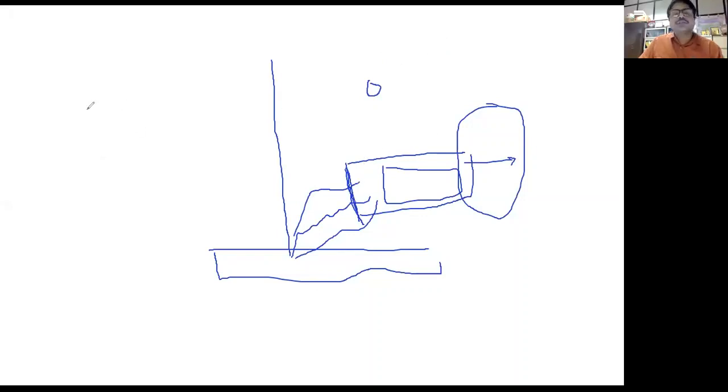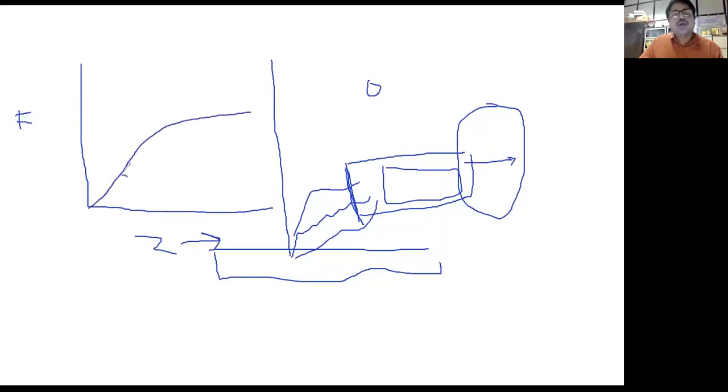And another point is the scattering cross-section for X-rays, this is called fluorescent yield. Suppose this is our curve, where this is atomic number, and this is fluorescent yield, which is basically a ratio of X-ray emission and Auger emission. I think all of you know that Auger and X-ray emission are competing processes. So when we increase the Z number, it starts increasing like this. So for the lower atomic number,